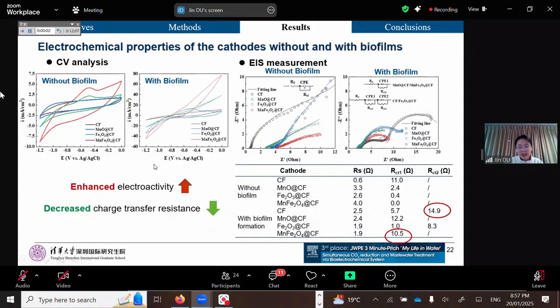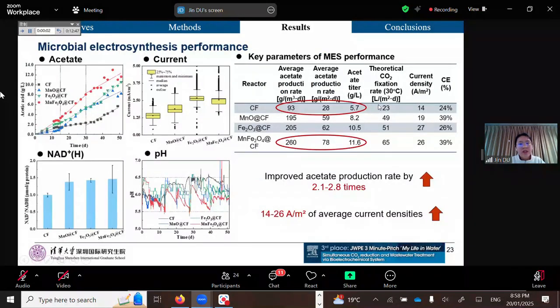Next, we compare the in-situ electrochemical performance of the 4 reactors. Before the biofilm formation, the CV analysis showed increased electrochemical activity for the manganese ferrite modified electrodes. And after the biofilm formation, the EIS analysis showed significantly reduced charge transfer resistance for the manganese ferrite modified electrodes, suggesting enhanced electron transfer between the electrode and the microorganisms. The acetate accumulation in the 4 reactors reached 5.7 to 11.6 gram per liter, with the manganese ferrite modified group performing the best. Its average acetate production rate reached 260 grams per square meter per day.